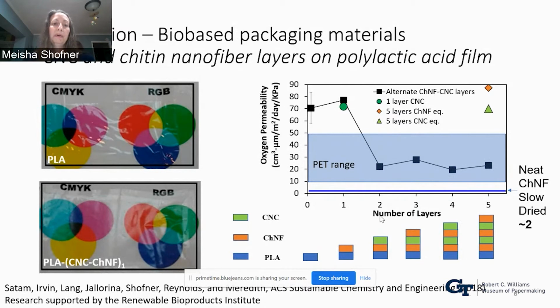And when we would put these layers on polylactic acid, what we see is, with just one layer, if this blue part is our PLA, and then we have one layer of these chitin nanofibers and one layer of cellulose nanocrystals, we see that the oxygen permeability decreases quite a bit from this uncoated material.